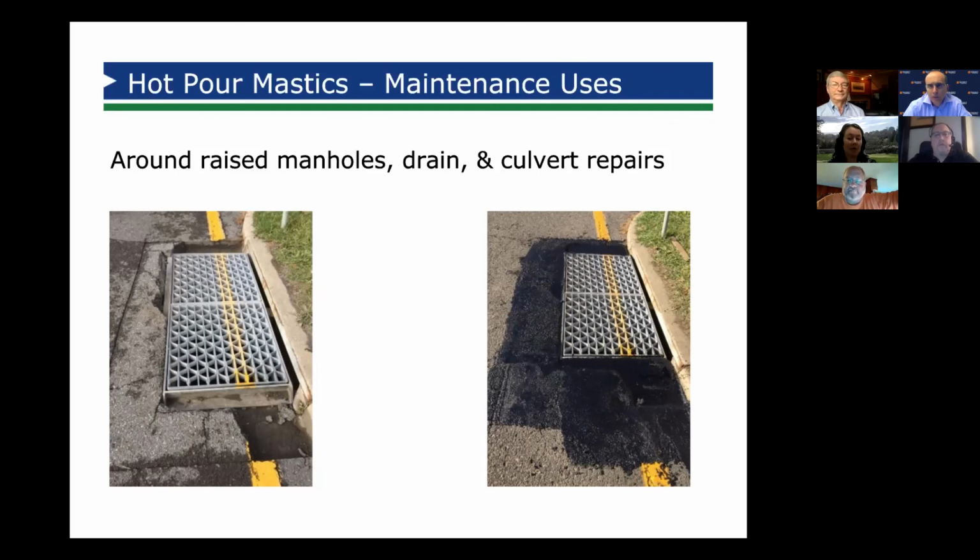Steve, maybe this one was for you. Does the product mill well off the surface, or does it pull out? Is there required patching before an overlay? Well, from our research, and you don't like to bring up negative things, but this might be the only thing that is both a positive and a negative. The positive that we've heard is that the material stays flexible, as Rick was saying, for years. And when they do milling, we've heard from other states that have had to go back and do projects where they were using wrap material, and they basically said it gets and stays so flexible that it gums up the equipment.